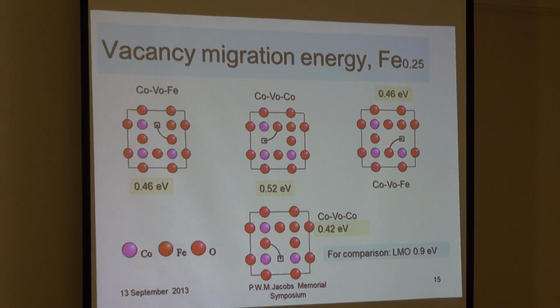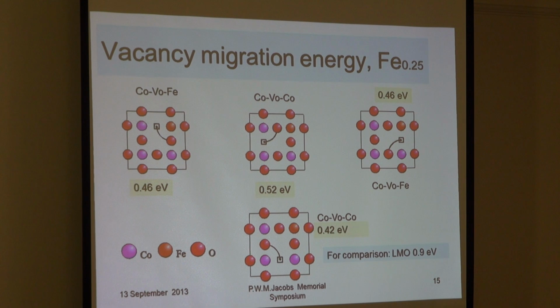And the next question is again about essentially not only formation but migration energies. So we also calculated migration energy for different configurations, and I mentioned that in the initial configuration and final configuration the oxygen vacancy has different neighbors. It could be cobalt-iron, cobalt-cobalt, and so on. So there are several configurations. We calculated all this, but you should be careful, because this structure is quite loose, and essentially this diffusion path is not linear, but it's curved. And if you don't take it into account, your migration energy could be in error by 50%.